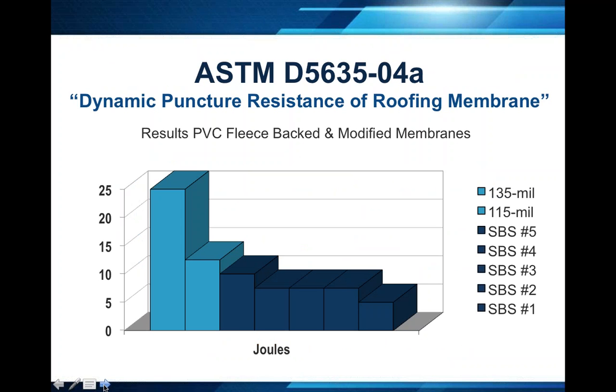That polyester fleece dramatically increases the puncture resistance of that membrane, and it outperforms in ASTM D5635. PVC outperforms a modified bitumen in terms of puncture resistance.